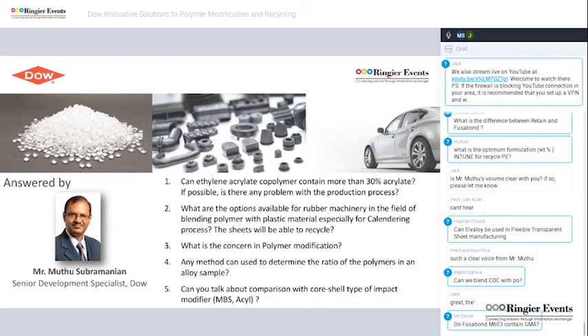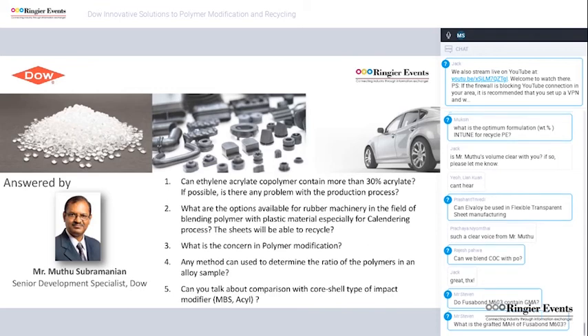Okay, the fourth question is, can any method be used to determine the ratio of the polymers in an alloy sample? Okay, for this, FTIR can be used to identify the chemical composition of the polymers in the alloy, and we also need to create a calibration curve by plotting the peak height or peak area for the known different ratios of those polymer blends. After that, using the calibration curve, it might be possible to determine the ratio of the polymers in the unknown alloy sample.